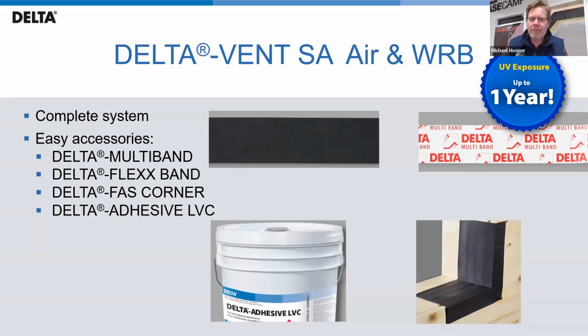With our self-adhered membranes and tapes, all of them are pressure sensitive adhesive. So I need to stress that it's pressure sensitive. You really need your hand rollers. You need to roll these. And adhesion, if you stick it on and then try to peel it off and say, hey, this doesn't stick, well, you're right. The reason why is it's a combination of pressure and time. The technical term is dwell time. Your adhesion will actually improve over time, typically 24 to 48 hours. When we do all our lab testing, it is a 24-hour dwell time before the tape is tested.